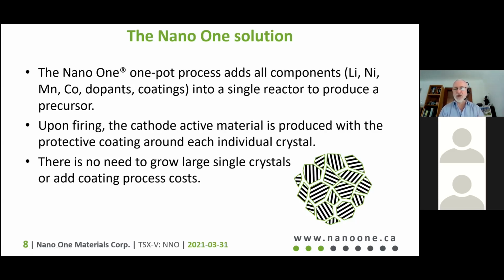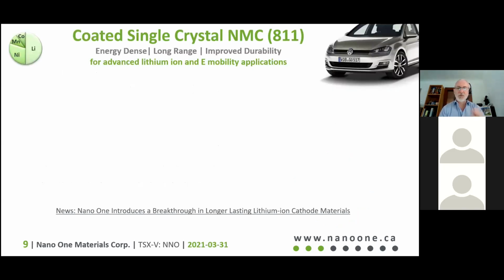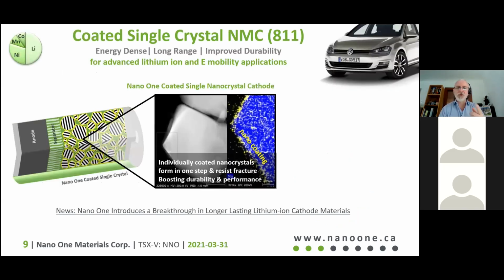And we can do that without adding any separate coating steps, and we'll show you the process in a little while. But what I want to show you is what we can do with it. This is a single crystal, an 811 high nickel manganese NMC material. And the picture in the middle is an electron micrograph of a slice through the crystal.